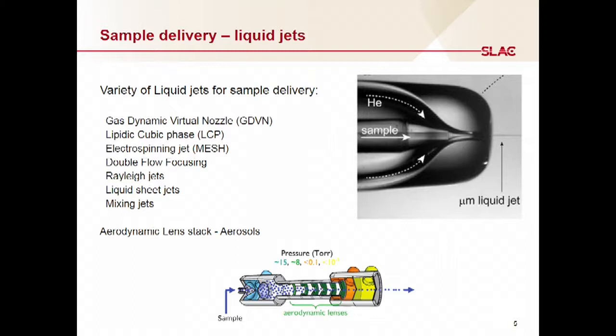Another thing that we have to think about is sample delivery, because it's 120 hertz. You want to replenish your sample quickly if you are working in the diffract and destroy regime. Diffract and destroy, you've probably heard this phrase quite a lot. We have a very intense X-ray beam, and so typically many samples are destroyed using a single pulse. And so if you're going to do 120 hertz repetition rate, that means you need to replenish your sample at 120 hertz. So for this, many sample delivery techniques and technologies were developed.